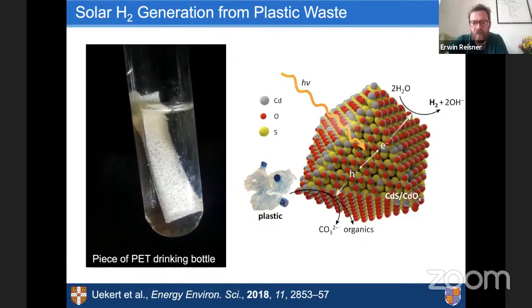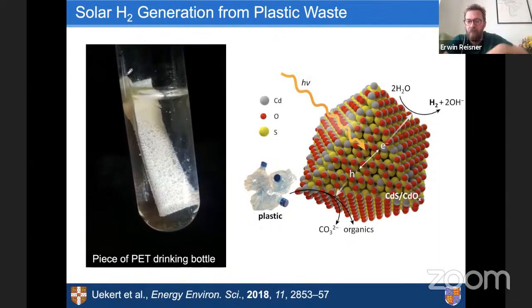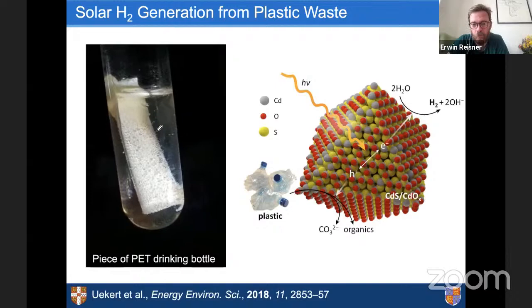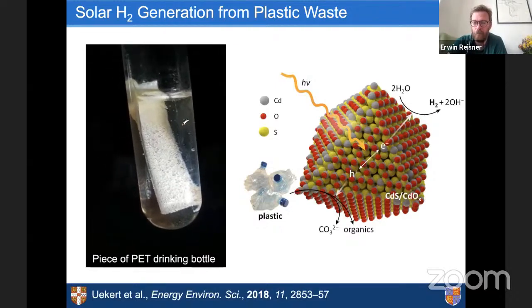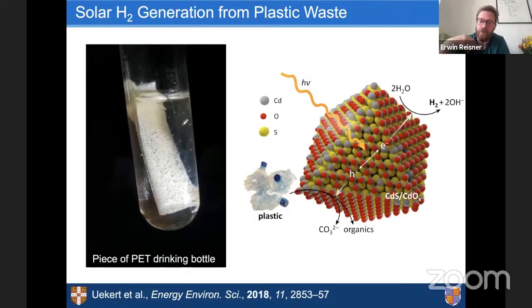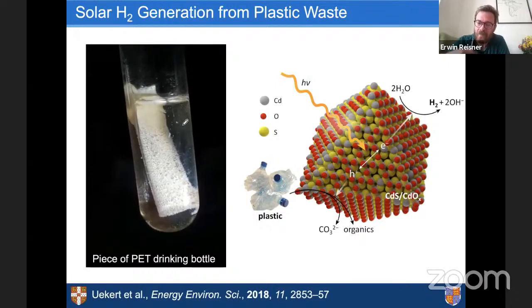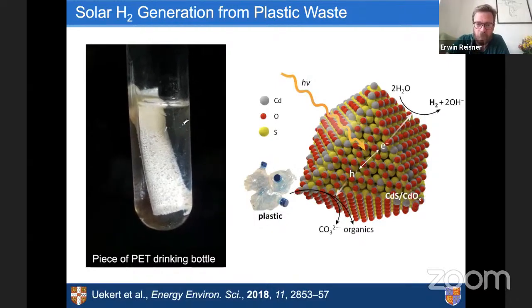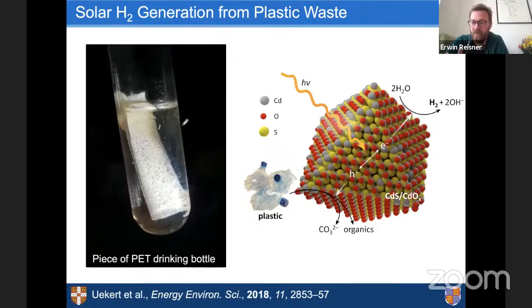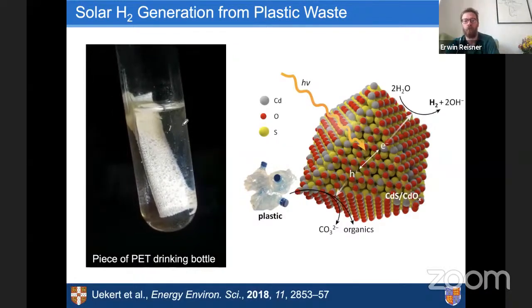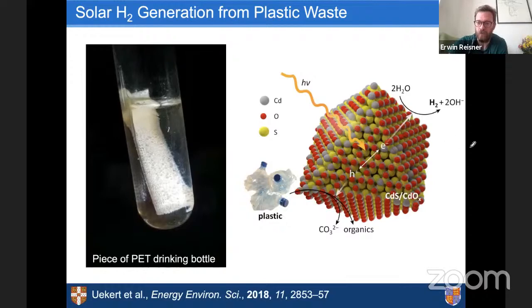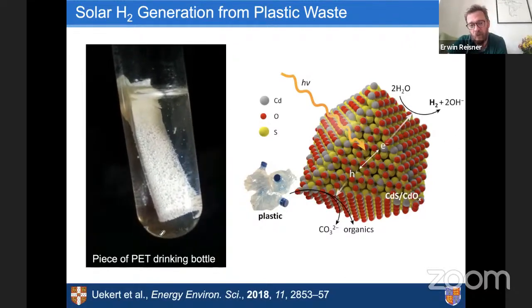But before putting it into the test tube, actually we coated it with this cadmium sulfide photocatalyst. And if you take it in and expose it to light, you can see now all these bubbles of hydrogen coming out. So exactly the same as before with this piece of wood, the cadmium sulfide starts eating into the PET, which means chemically speaking, oxidizing the PET and releasing the electrons by the cogeneration of the hydrogens. I think it's a very nice illustration how the systems work. But you can also see that this is not an overly efficient system, right? So it will probably take us weeks to consume all of this PET or even longer at the moment.